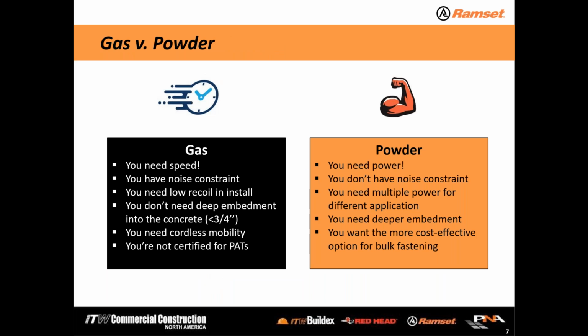Why we use gas versus powder. So these are the two basic systems that the Ramset brand offers. Gas, you need speed. Again, as fast as I can push down, pull the trigger and let off, I get a pin to come out. Most of our gas tools have at least a 40 pin capacity, so I can do that 40 times. Powder, with a powder magazine, I can do that up to 10 times. So the big advantage for gas is in that bullet point number 3, low recoil. It's very, very easy to use, easy on the operator, not a lot of fatigue when using a gas tool.